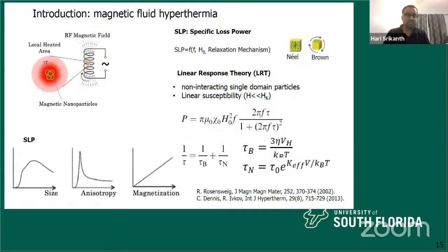There's a size dependence, which is very important. We cannot work with small particles and we cannot work with large particles. The best particles are somewhere intermediate. They're close to the single domain limit, but not quite superparamagnetic. There's also an important health reason why we cannot use very small particles. And I'm talking about particle sizes smaller than 10 nanometer.